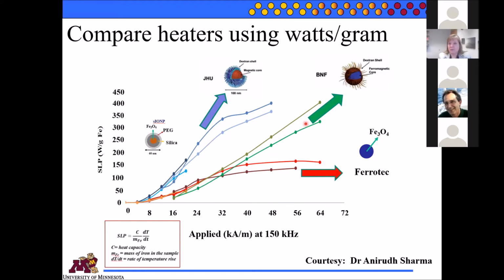If you want to compare heaters, most people use watts per gram as one measure of how good this particle is versus that particle. So these are the different particles that I showed you on that first slide, and what kind of watts per gram they're getting, specific loss power. So you see about hundreds of watts per gram iron, and these are all at increasing magnetic fields, and all of these measurements are at 150 kilohertz.